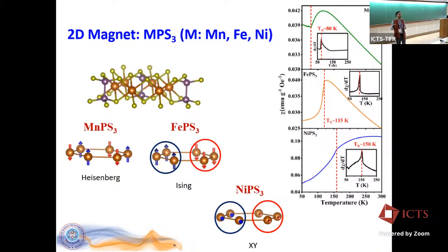All right, now I come to the systems that we have studied. We have studied the transition metal phosphorus trisulfide systems, which are basically manganese phosphorus trisulfide, MnPS3, FePS3, and NiPS3. If you look at the crystal structure, this is just one layer. Of course, if I have to build the structure, I need to have at least 2 layers of it, because at monolayer level, the crystal symmetry changes, okay? So whatever data that I'm going to show are not monolayer, but above that, okay?